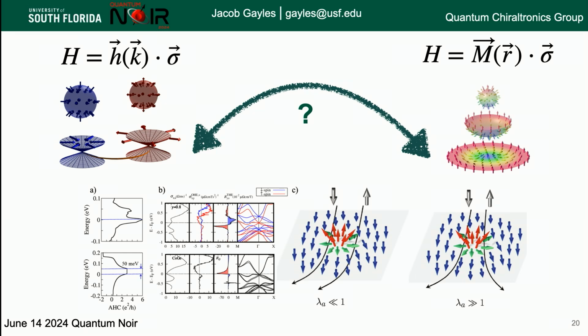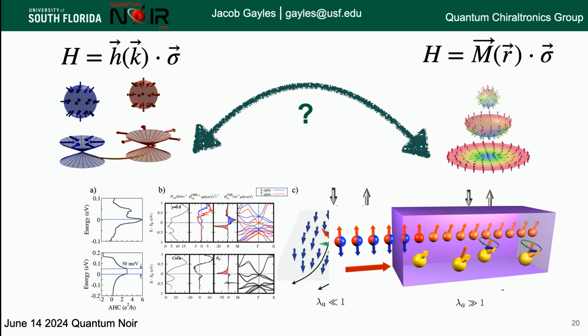And then also when the skyrmion affects the Weyl, you can open a gap. And because that gap is inverted, you get what's called the quantum anomalous Hall effect, which Pablo Herrera talked about a lot. And that's also nice for computing devices. Good. And last thing, of course, is to manipulate the spins. Because in these Weyl materials, this momentum vector here is essentially your current, right? This is your internal current in your system, but when you couple the spin to it, you produce spin currents, and that is the most efficient way to manipulate these skyrmions. So there's a lot of different avenues one can go here.